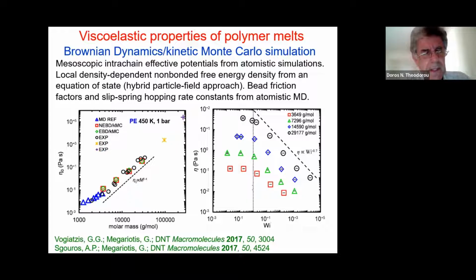Now, if we use this model, we can try to get out some properties, and you see here some rheological properties. On the left-hand side, you see the zero shear viscosity of polyethylene melts over a variety of molar masses. You see that there are some atomistic simulations from molecular dynamics here. These are shown with the blue triangles, and they are necessarily confined to low molecular weights because we cannot address the long times of the longer chain systems. However, with the mesoscopic approach, we can go to larger molar masses. So you see two sets of results, the green points, which come from equilibrium Brownian dynamics kinetic Monte Carlo, and the red squares, which come from non-equilibrium Brownian dynamics kinetic Monte Carlo under conditions of steady shear flow.